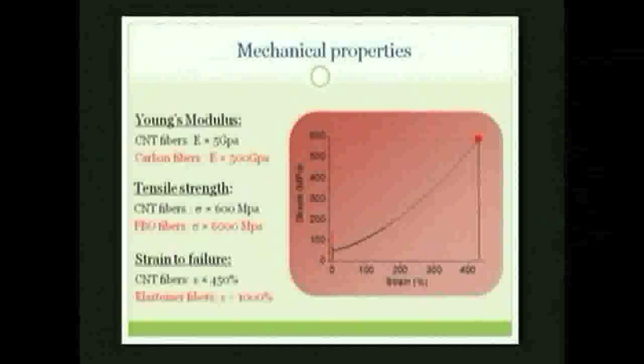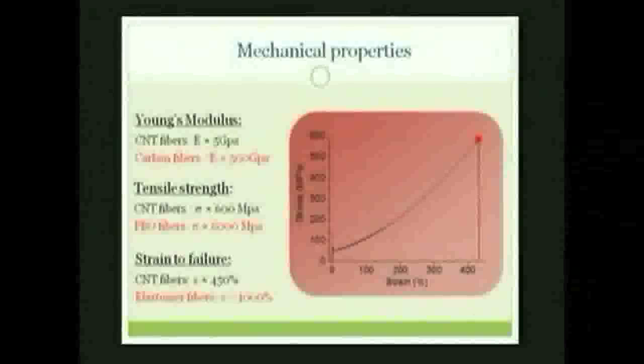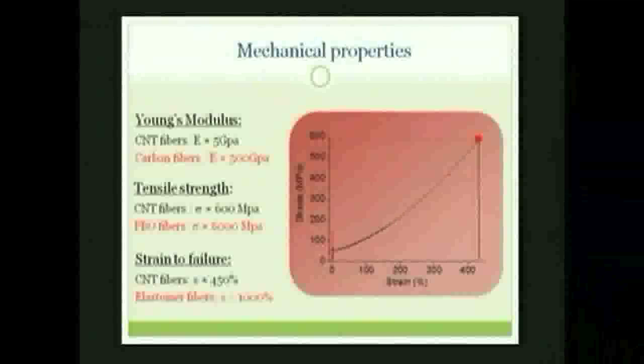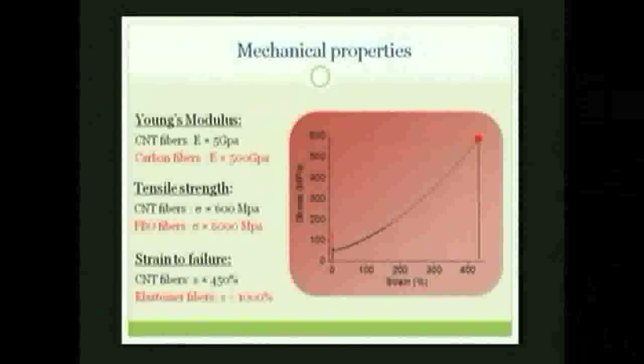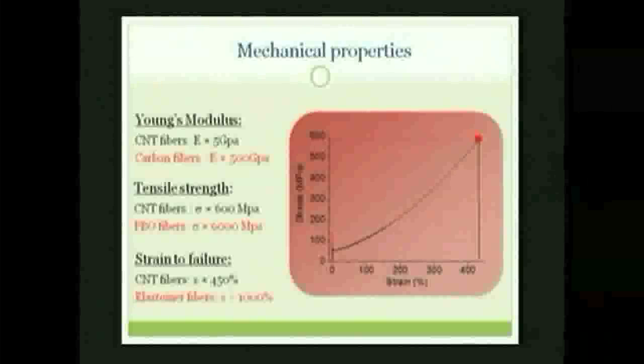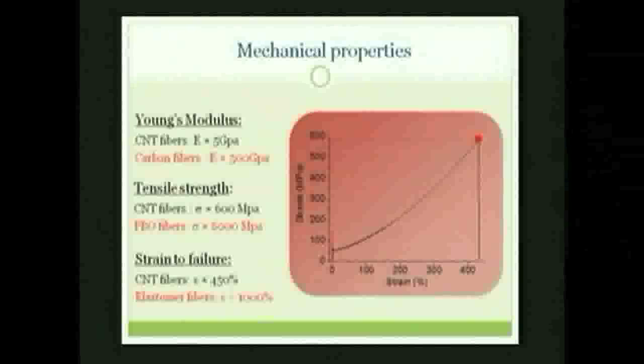This is a tensile stress experiment, as I've shown before, okay? And this is the behavior of our fiber. So here you have the slope of the elastic regime. The elastic regime is very short. And then you have a very, very long plastic regime. And here you see the failure, the breaking of the fiber at this point. If you calculate the Young modulus, it's 5 GPa. Just to give you an idea, it's not so bad.